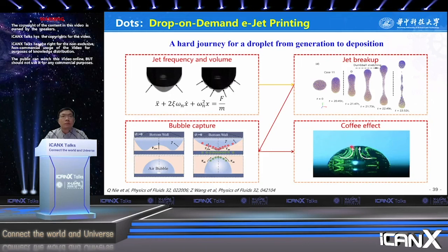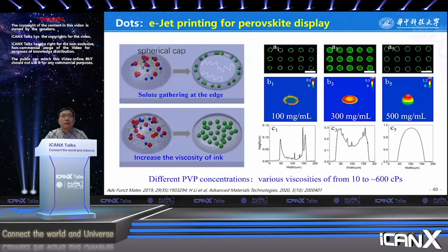Finally, beautiful liquid jets without satellite jets, without air bubbles, silently lie on the substrate. In this mode, it just wants to become a solid state and keep the appearance at the same time. However, the coffee ring is ubiquitous in printing, and it is also inevitable in printing. It is a result of the solute gathering at the edge of the dot.